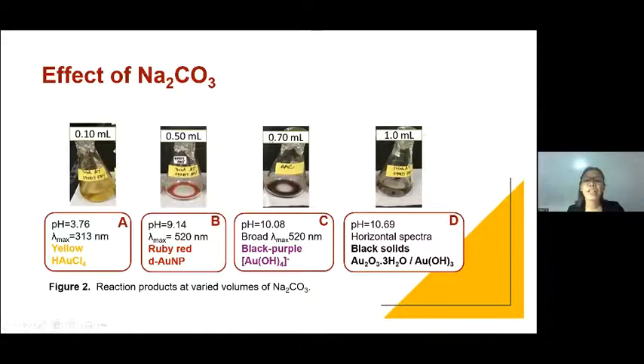Reaction mixtures with 0.7 and 1 ml are cases of excessive hydroxide ions, and the result is a broad band, low absorption at 520 nanometer, and even horizontal spectra for 1 ml sodium carbonate. The excessive hydroxide brought about speciation that produces black-purple and black solids precipitate that even cause aggregation.